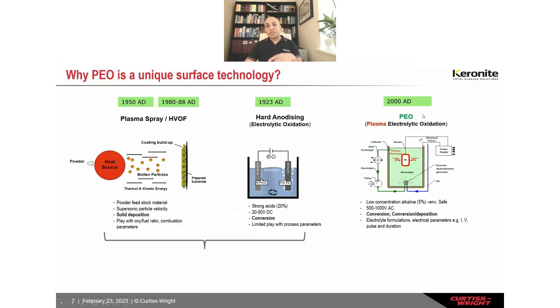So you move on to PEO as a technology, which was commercialized around 2000, as you can see. The main fundamental difference between PEO and anodizing, for those who are not familiar, is that both are electrolytic. There are similarities. Unlike the thermal spray here, which is a solid state deposition and additive process, this is probably a subtractive process. You dissolve the surface and convert that into aluminum oxide, primarily amorphous alumina.